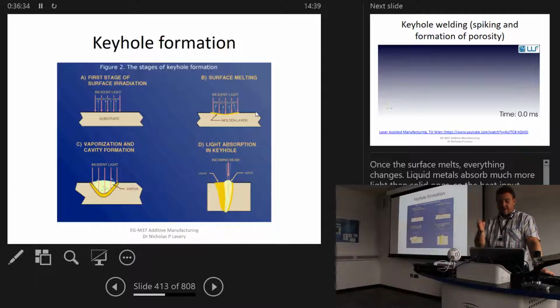So there are various stages that you have to go through before you can transition from conductive to keyhole. First stage, the laser's hitting the surface, we start to melt, it forms a melt pool, the heat is nicely conducted through, and you get a relatively elliptical shape. At some point, if you keep on putting energy into it, you're going to start to vaporize the material that you're putting the laser onto. And what happens then is that it starts to vaporize, and the vapor forms a plasma. And sometimes just below the surface of the material, that plasma takes in the laser and spreads it out, and rather than the reflection you can see in the first stage of the conduction, it means that you can't get that much energy into it.